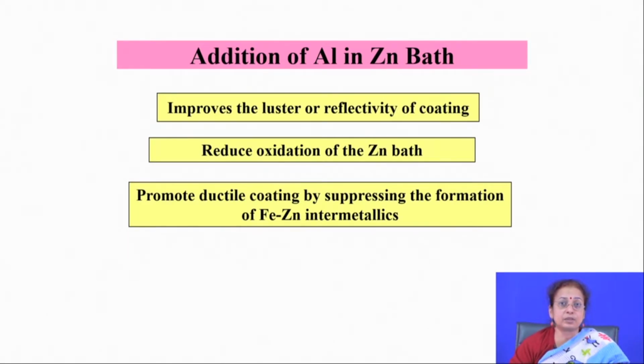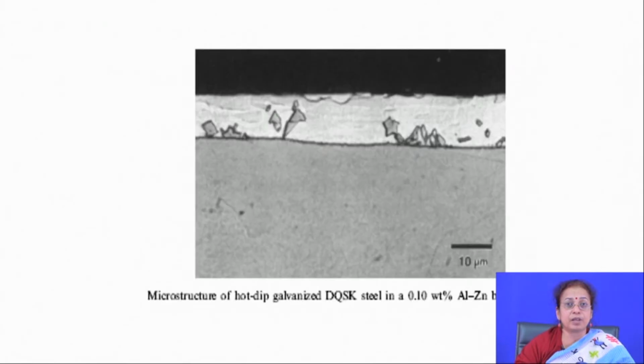Usually in the zinc bath a very low percentage of aluminum, up to 1%, is added, which serves all these purposes. So, you will find that the iron zinc intermetallic formation kinetics is reduced. But apart from 1% aluminum, there are also two more aluminum percentages which are added in the zinc bath by changing the composition itself. One is 5% aluminum, another one is 55% aluminum, which are called galfan bath and galvalume bath.